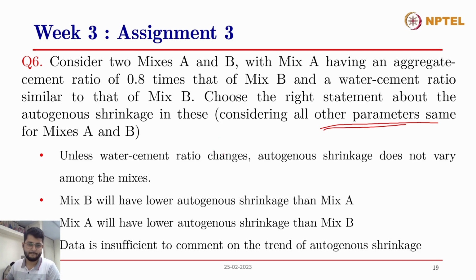Yes? Yeah, I will respond to that. Right, go ahead. It is stated that mix A has an aggregate cement ratio of 0.8 times, so aggregate content is comparatively lower. Higher aggregate content means there will be lesser autogenous shrinkage. So the first one is incorrect. Mix B will have lower, yes, because of higher aggregate content relatively as compared to A. The third one is incorrect, and the fourth one is also not correct. So mix B will have lower autogenous shrinkage than mix A because of higher aggregate content. Okay, correct. Thank you.